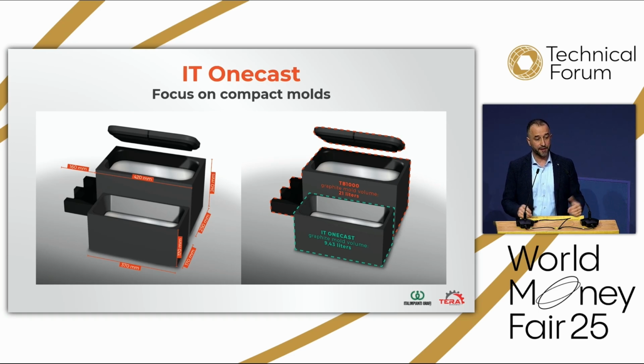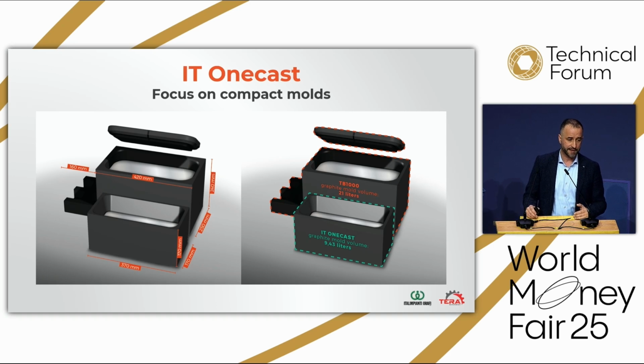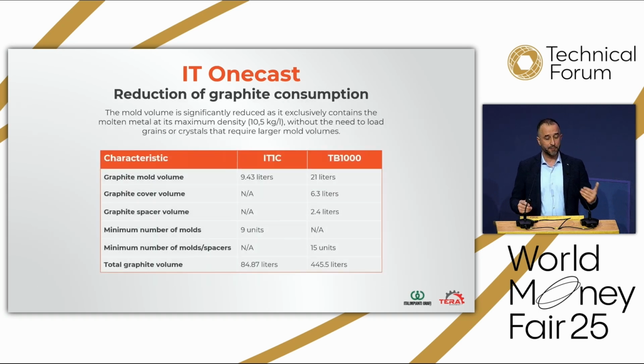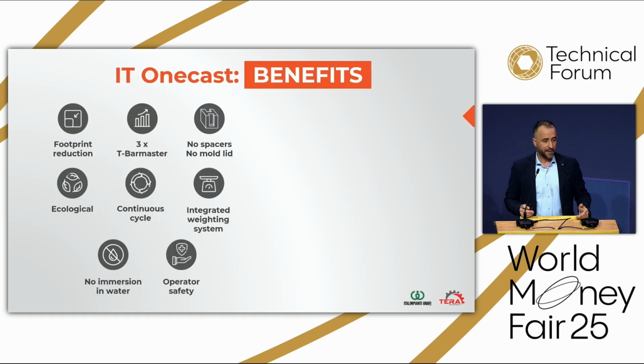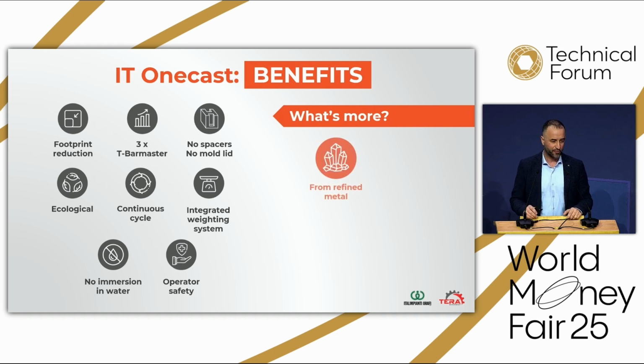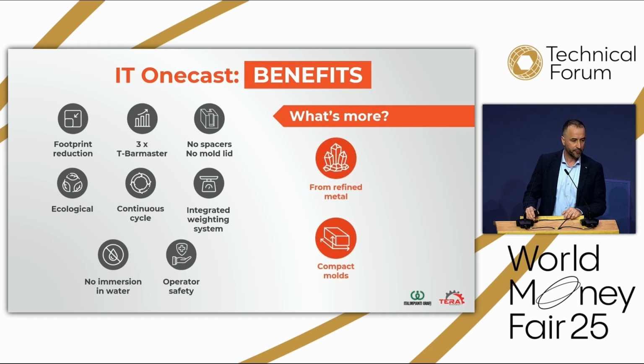This is an example of the difference between the traditional molds for casting 30 kg or 1,000 ounce silver bar, with the traditional on top and the one cast on the bottom. And this is a simple table where we can see in overall consumables involved in the process, we have like 80% less compared to the traditional systems. Key benefits, I think I've gone through the main ones, but summarizing: reduced footprint, higher efficiency, no spacers, no lids, so ecological and 5.0 compliant.